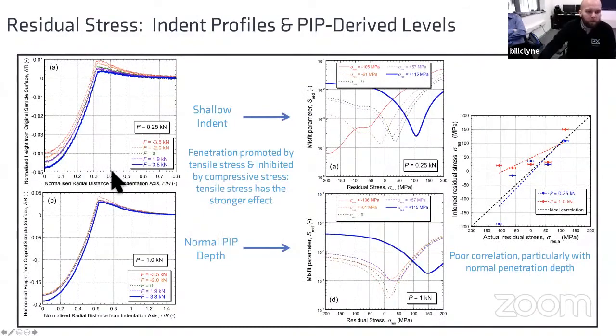So we can see here the results of the indentation experiments for different applied residual stresses. This is written just as applied loads. And we can see here at the applied indentation load of 1/4 of a kilonewton that there are some differences between the indentation experiments. When we increase that load to a kilonewton and therefore go a lot deeper, we can see that the effect of the residual stress is much weaker. So there is not that much separation between almost all of the cases there.